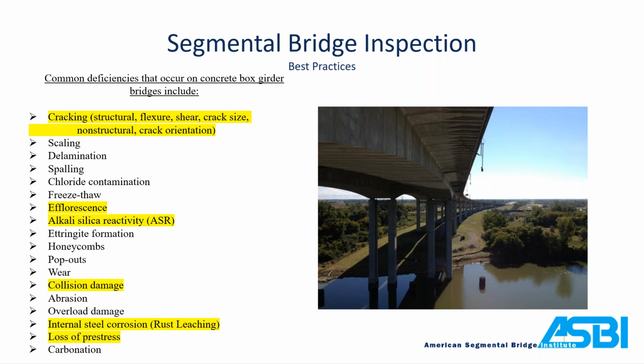In those instances, you can take a core. A lot of departments and bridge owners can tap into some geo experts that can do an analysis and determine if it's actually an ASR issue. Collision damage, again, these are long structures. If you have 1.5 mile, 2 mile long structures, they're just more susceptible to cars running into barrier walls and banging things up. Internal steel corrosion, again, whenever you see rust leaching on a segmental bridge, it raises a red flag. You need to do a deeper dive into that. And then loss of pre-stressing, you'll see some cracking around your anchorage terminals or some tensile flexural cracking as a result of those loss of pre-stress forces.